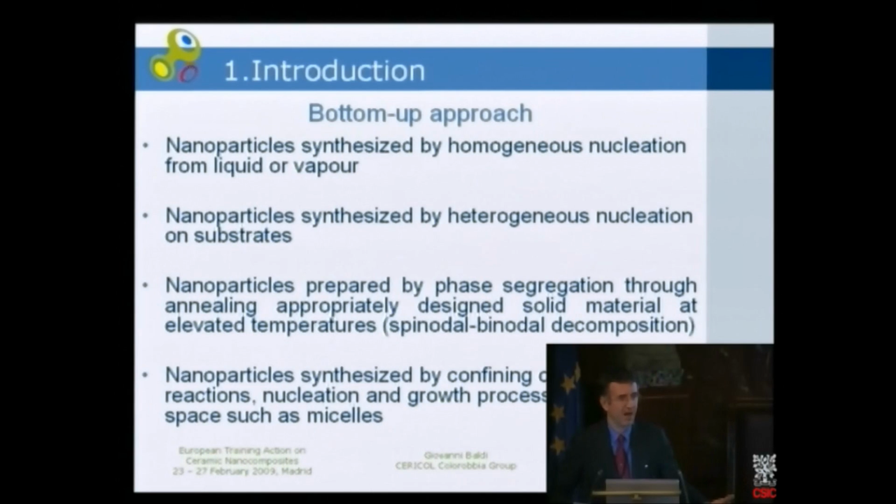It could be used, for example, in the glass ceramics approach, in which we have a spinodal or binodal decomposition in small liquid phases that can then crystallize, and so the shape of this area can drive the shape and the size of the crystallites. Finally, nanoparticles can be synthesized by confining chemical reaction, nucleation and growth processes in small spaces. This is the case of the inverse micelle approach.